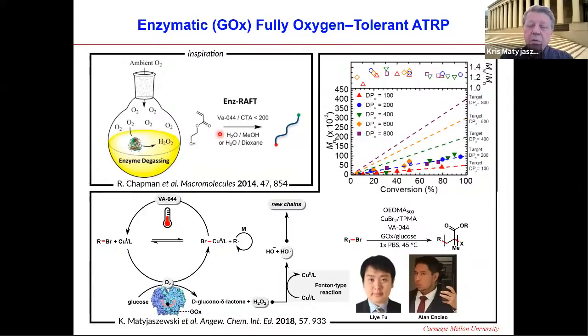So the first example was reported by Professor Yusuf Yagci from Istanbul University for conventional radical polymerization. He used glucose oxidase and ran the reactions essentially in a system open to air. Then later it was adopted by Bob Chapman for the enzymatic RAFT process. So here the glucose and glucose oxidase could consume oxygen, forming hydrogen peroxide, which is typically a very poor initiator under conventional radical conditions. In ATRP, it's a little bit different, as you will see in a moment, but we tried to do exactly the same process.